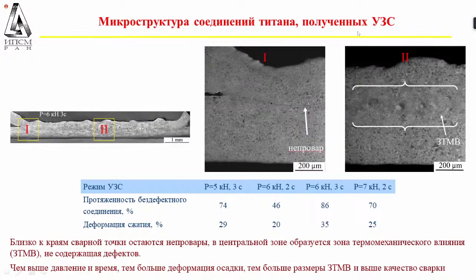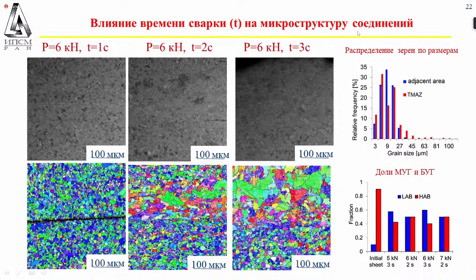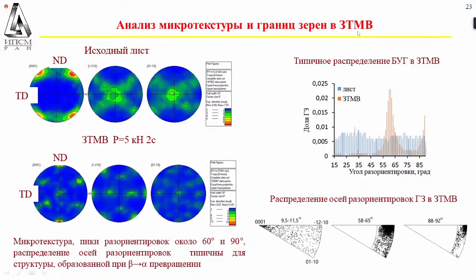Of course, you can see some defects at the edge. So the higher the pressure, the more deformed the surface is. And we also get the thermal mechanical influence. And we concentrated on the research of this very area and the microstructure which derives in this area. So we have taken the industrial sheet of titanium. But anyway, we can see that grains were grown on this sheet, and the sheet was deformed, and microstructure was developed there.